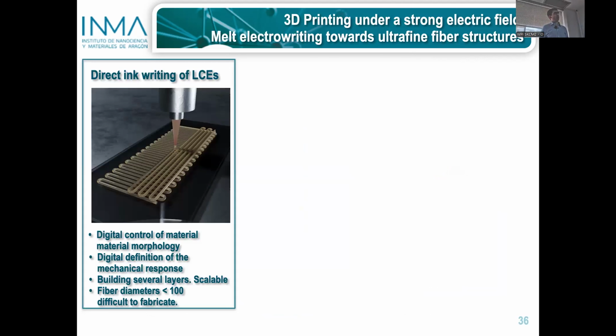As I said, we are also trying to push the limits of our technology. We see that we have a limitation in terms of the fiber diameter. You cannot go to nozzles that are below 100 microns, because then the pressure is too big, and you cannot generate fibers in this nozzle.